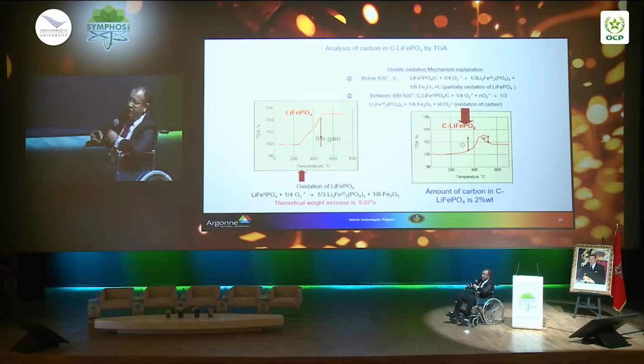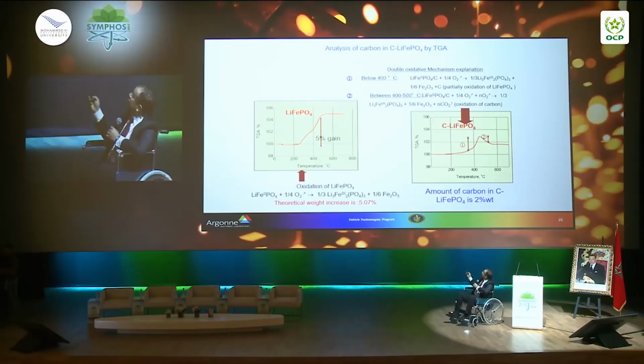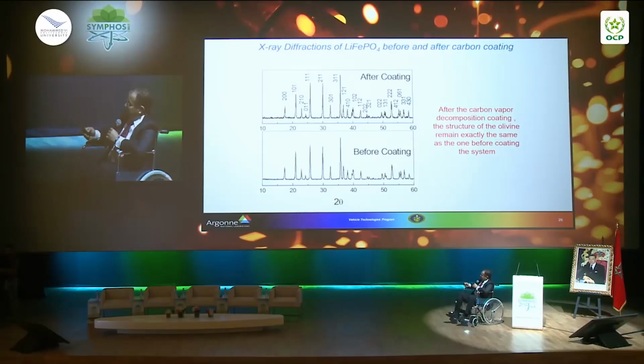In general, when you have nanomaterial, you have to put 10 to 15% of carbon, and that can also affect the cell because you put inactive material in the electrode. But with this clever cracking of toluene or propylene, you can put a very tiny amount of carbon, less than 2%, and the performance is very outstanding. This is an X-ray that shows that the coating does not affect the overall bulk structure of the material. As you can see, before and after is exactly the same.